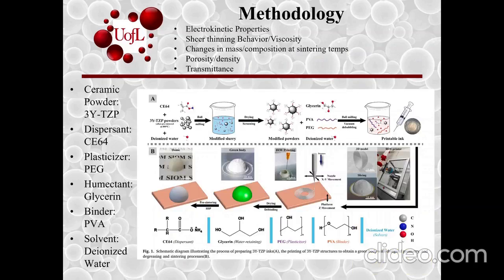So this slide has a lot of information on it. There's a lot of good and useful information. First, I'll point your attention to the stack of bulleted items on the left side. These are all the ingredients to this ceramic ink, namely the ceramic powder, 3Y-TZP, a dispersant, CE64, a plasticizer, PEG, this humectant glycerin, a PVA, which is a binder, and the deionized water, which is a solvent.